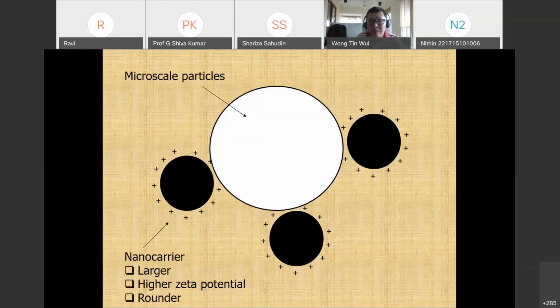Now you can see that when the nanoparticles are larger and rounder, they will have a lower specific surface area. So the nanoparticles will not interact among themselves, but instead will be absorbed and sit on the surfaces of the microscale particles. Thus, this will enhance their inhalation into the deep and peripheral lung with the help of the microscale particles. And nanoparticles that have a higher zeta potential tend to repel each other, so there will be a lower level of nanoparticle aggregation. Most of the nanoparticles will absorb on the surfaces of the microscale particles and be brought into the deep and peripheral lung.